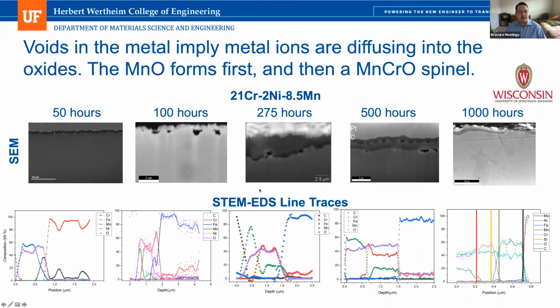Also, we've done STEM EDS line traces on these samples, and it starts to give us a very good idea of what the compositions of the oxides that are forming are. And we see some interesting behavior. So right on the surface at the very beginning, so this is 50 hours, we see the manganese oxide layer form, and we have a fairly large oxide layer. But then we have a thinner oxide layer that seems to have manganese and chrome. So there's a manganese chrome oxide spinel that's forming.